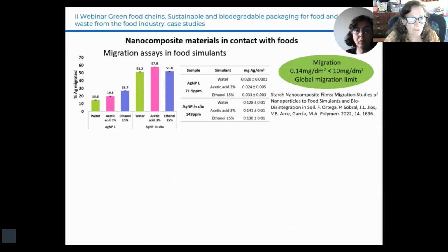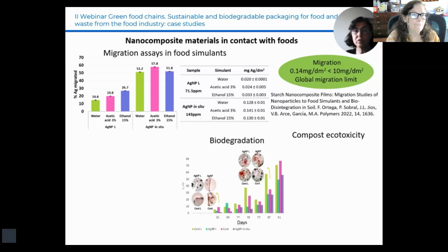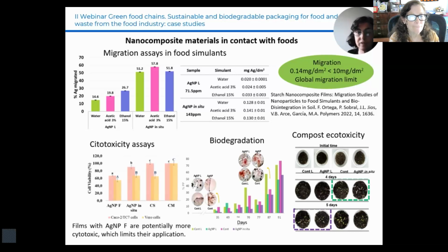However, in the case of nanocomposite material in contact with food, further tests are necessary to study their safety. For this purpose, migration tests of silver nanoparticles into food simulants were performed, demonstrating in all cases that the migration was below the global migration limit permitted by international regulations. The cytotoxicity of the materials was also studied on 2 model cell lines, Caco cells and Vero cells. It was observed that in the case of nanoparticles obtained by laser ablation, cell viability is lower and therefore they could be potentially cytotoxic. Biodegradation in soil was evaluated, which was not affected by the presence of the nanoparticles. In this case, it is necessary to evaluate the ecotoxicity of the remaining compost, showing positive results in this regard.